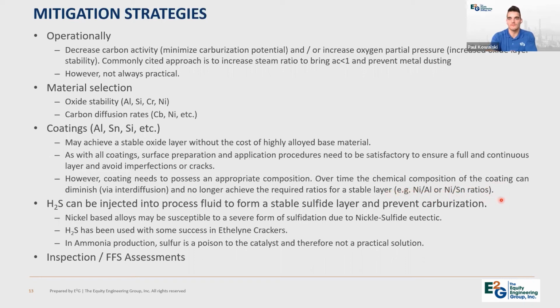So, that ratio may start as satisfactory, but over time it reduces and the coating is no longer protective. So of course, again, the coating providers and manufacturers, they'll add specific alloying elements to really try to minimize or reduce the interdiffusion effect so that the coating stays intact and the correct chemical composition for the entire life of the asset.